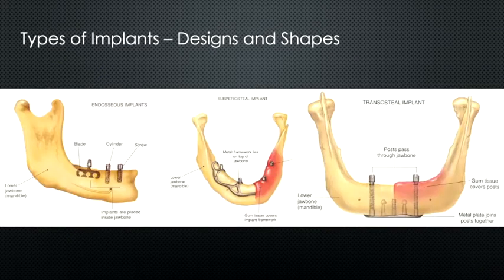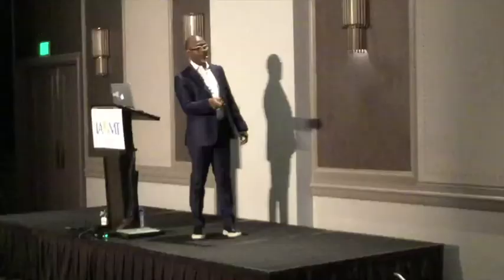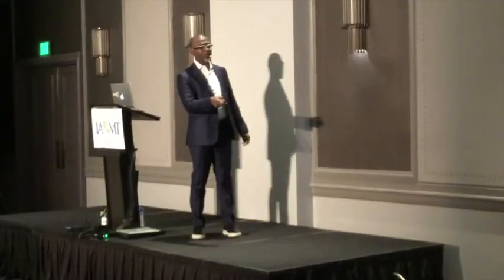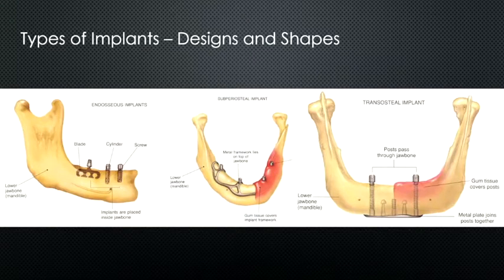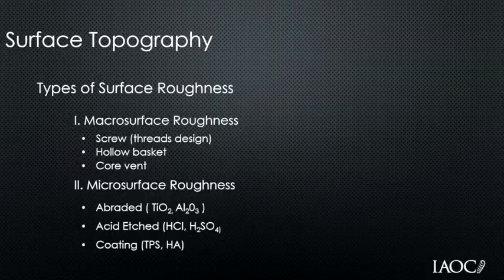And you also have the transosteal implants, which nobody really uses. I see more zygomatic implants being done these days than having implants going right through the mandible because these were prone to fractures. Okay, these are making a quiet little comeback, not in big time. It's really for extreme cases, and they can be CAD/CAM'd, but they're not ready to be made into ceramics because the neck here is going to be a weak spot and an area of fracture if you ever try to replicate this in ceramics today. So things change very fast.